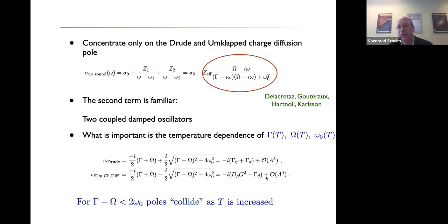In fact, the similar sort of dynamics of 2 coupled diffusive modes was already illustrated in a somewhat different context by Delacretaz, Gouteraux, Hartnoll, and Karlsson, who looked at decaying charge density waves. And they wrote down this effective formula. If you actually take this Umklapp hydrodynamics that we have, and you focus only on these 2 poles, right? You forget about the Umklapp sound poles, you can rewrite this in exactly the same way. These are these 2 coupled damped oscillators that contribute to the conductivity.